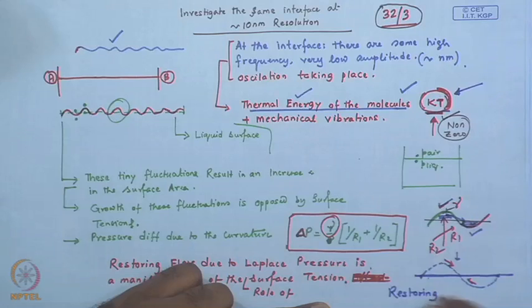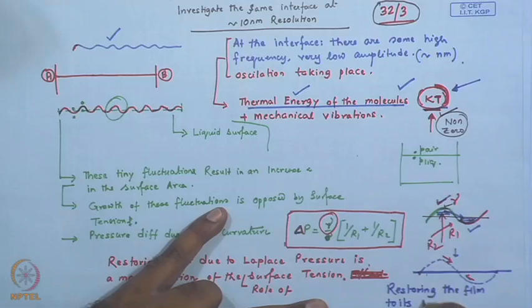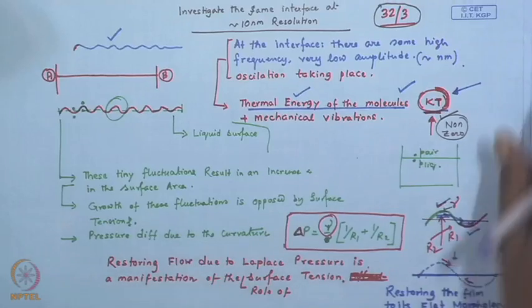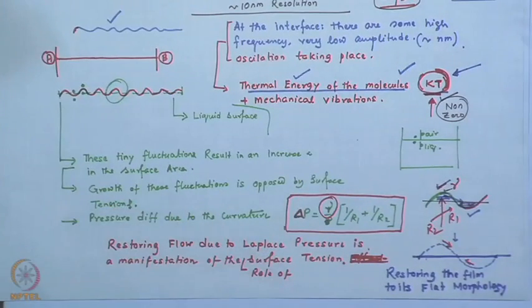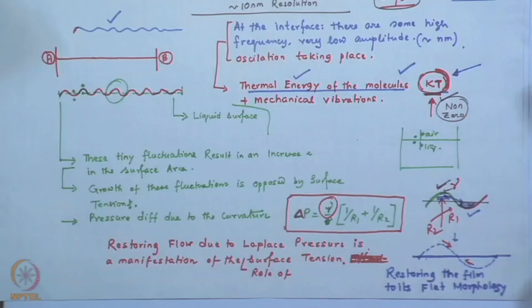So, this we understood. Now, in a macroscopic situation, these tiny fluctuations have no significant implication because they have a typical amplitude of the order of a couple of nanometers. So, in the macroscopic length scale, even if a layer of liquid is a couple of centimeters thick, these are very insignificant. And these fluctuations are provided by the thermal energy of the molecules, but there is no additional driving force for amplification of these oscillations.